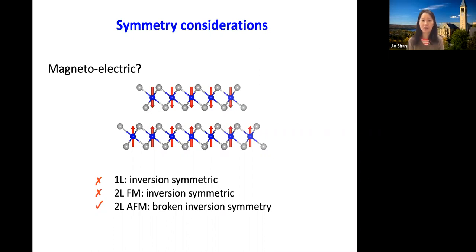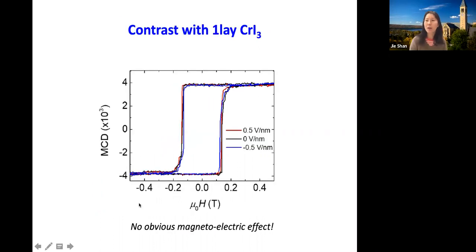So just from this simple symmetry argument, we know that we only expect to see linear magneto-electric effect in bilayer antiferromagnet. Just for a sanity check, we study monolayer first. We put this between two gates and then apply a perpendicular electrical field. And we apply already a huge field, on the order of 0.5 volt per nanometer. And as you can see, the MH curve of monolayer barely changes. So there is no obvious linear magneto-electric effect, and this is consistent with our symmetry argument.